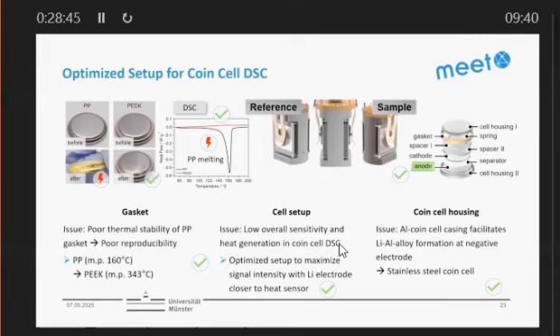Then we also changed the position of the lithium metal anode. We brought it very close to the sensor, which basically means that you have to put the lithium metal anode in the bottom of the cell and not in the cap. Because the sensors, these are sample holders, and they are made in a way that usually the cathode is close to the sensor. And finally, also for the coin cell housing, you have to be careful that if you use aluminum, don't use it on the anode side. Use it on the cathode side, because otherwise you have lithium alloy formation.